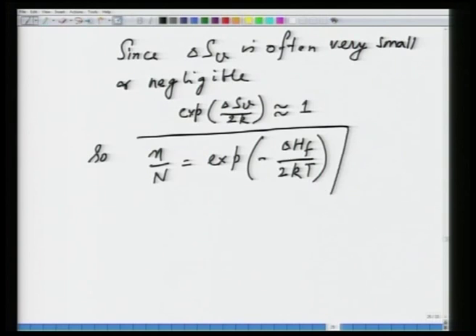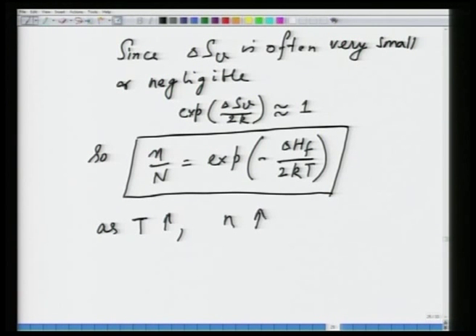So, this is your standard expression to calculate the equilibrium concentration of defects in a ceramic material or in an ionic solid. Now, this expression tells you that n is an exponential function of temperature and enthalpy of formation. So, as temperature increases, n increases, and as delta H f increases, n decreases. So, what you will see is that most of these ceramic materials have appreciable intrinsic defect concentration at higher temperatures. At lower temperatures, they do not contain a significantly larger number of defects.